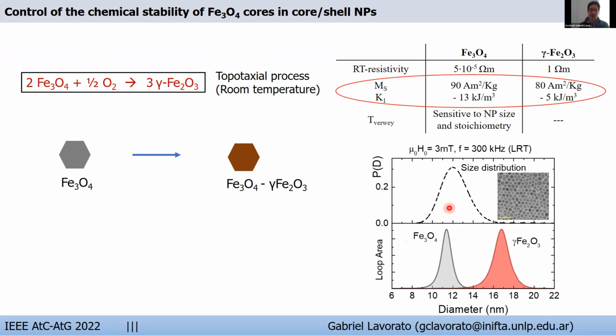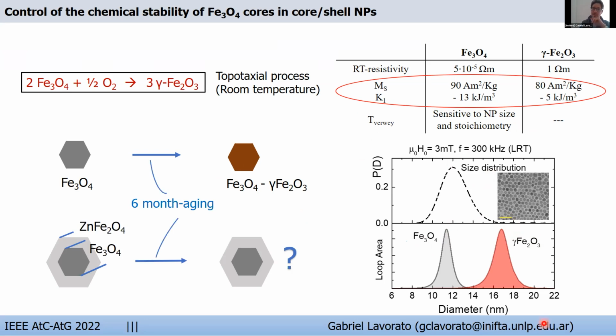This means that our fine-tuning of the size and magnetic properties will be lost due to the oxidation of magnetite. And this is really a problem for applications where in vivo conditions are required. So with this in mind, we wonder if the core shell structure is able to preserve the magnetite cores from oxidation. And to answer this, we aged both cores and core shell samples for 6 months under environmental conditions, and we studied the obtained products.